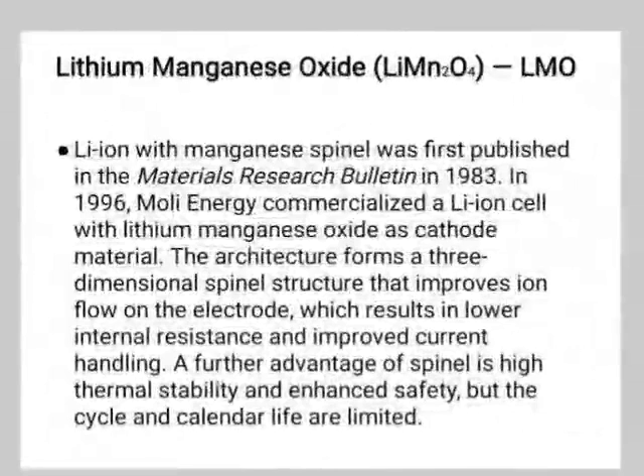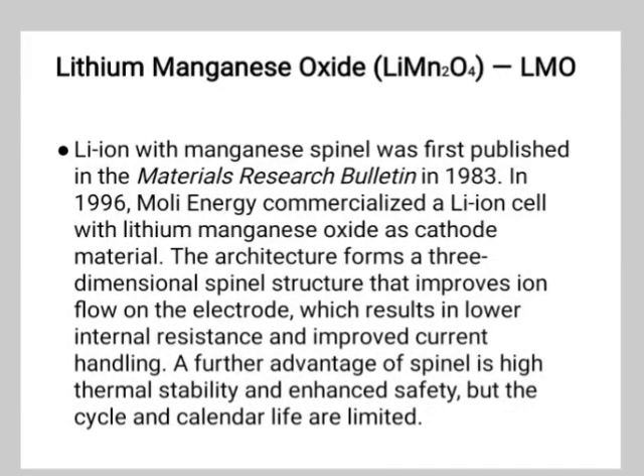Next is lithium manganese oxide — LiMn2O4, also called LMO. Lithium-ion with manganese spinel was first published in the Materials Research Bulletin in 1983. In 1996, Moli Energy commercialized a lithium-ion cell with lithium manganese oxide as the cathode material. The architecture forms a three-dimensional spinel structure that improves ion flow on the electrode, resulting in lower internal resistance and improved current handling. A further advantage of spinel is high thermal stability and enhanced safety, but cycle and calendar life are limited.